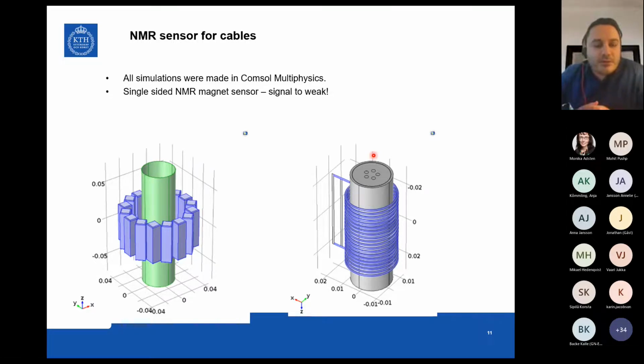So we started to do a series of simulations in COMSOL. One of the simulations we did was on the arrangement of the permanent magnets to get the highest magnetic field strength in the center. The image you see to the left is a constellation which we call a Halbach array. By placing these magnets in a certain array like this, you can maximize your magnetic field strength in the center. So we did a series of simulations to establish which Halbach configuration is going to yield the highest field strength.